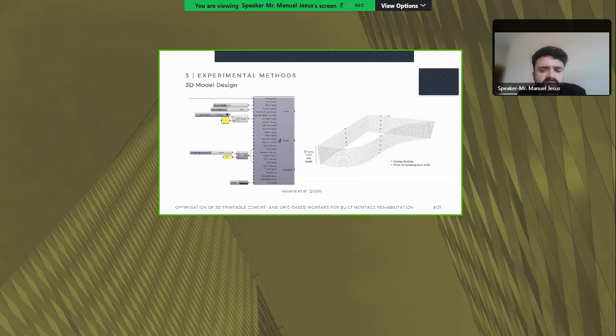Regarding the 3D model design, the printing path was programmed in Grasshopper, as I said, and translated into G-code using the Termite plugin, which is optimized for Delta WASP printers. The test geometry was designed to evaluate material behavior across different levels of geometric complexity, as you can see in the figure on the right. And the samples were printed to a height of 50 millimeters, consisting of 20 layers.